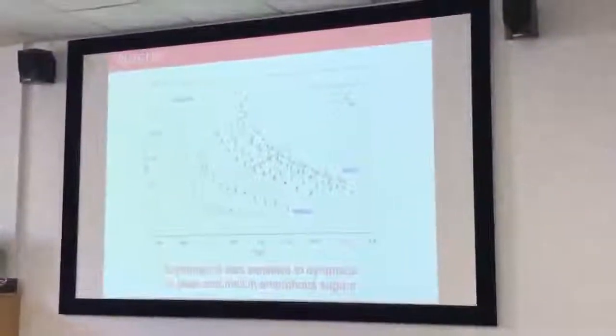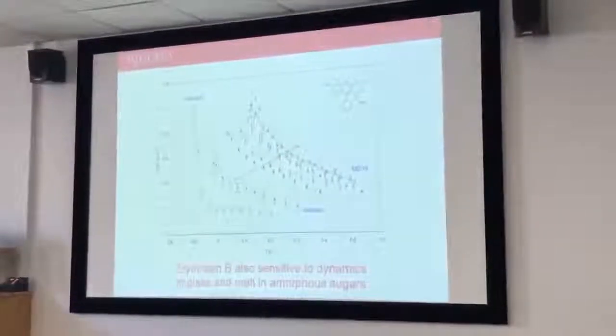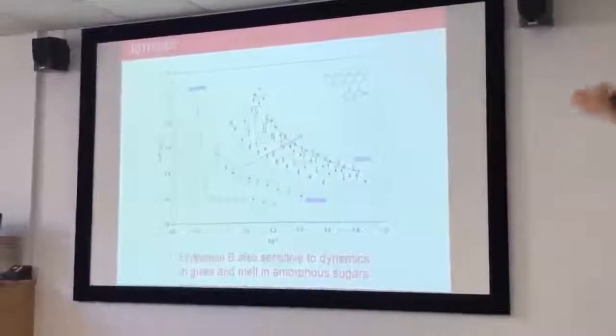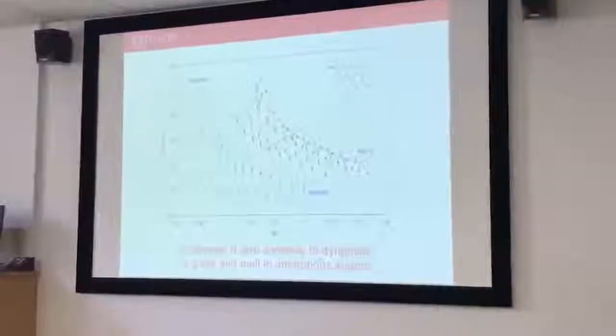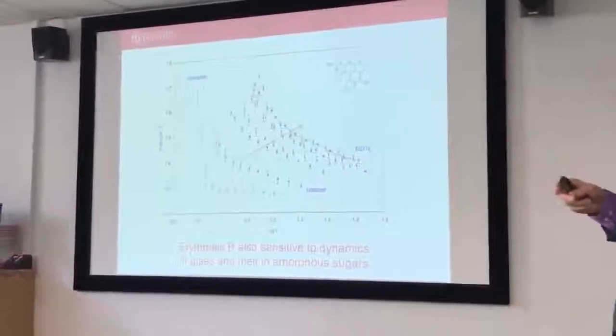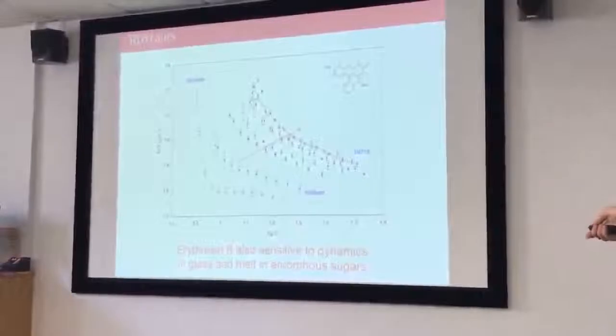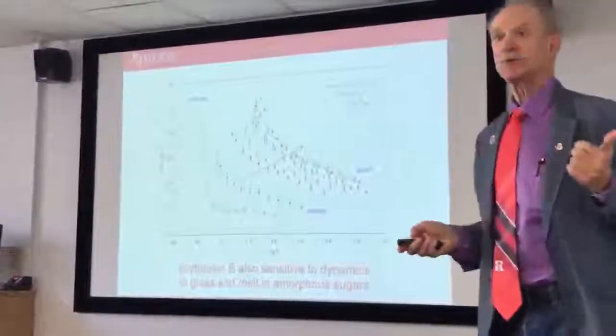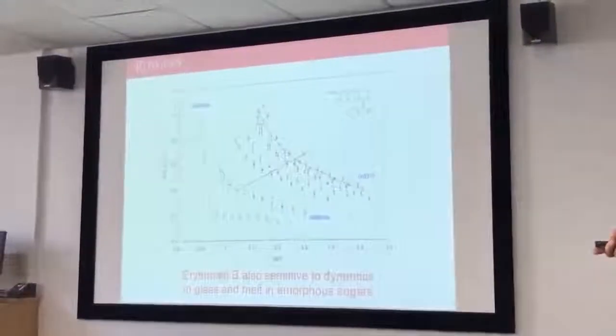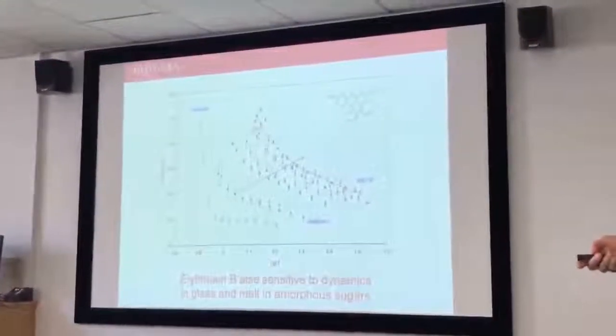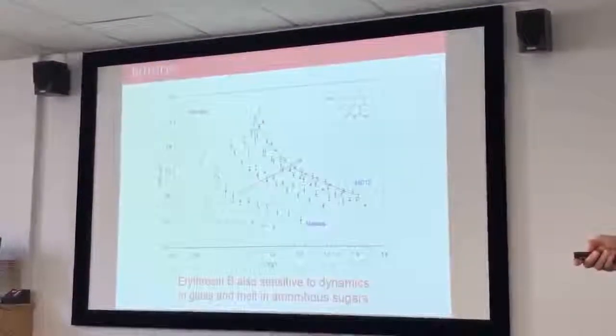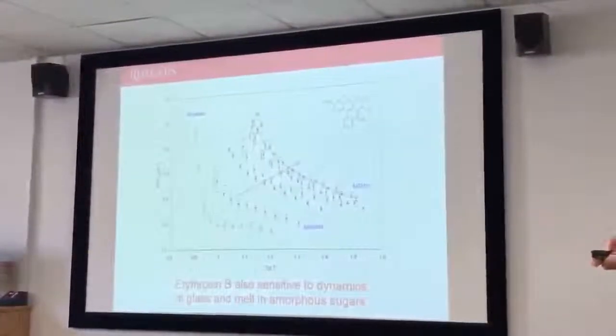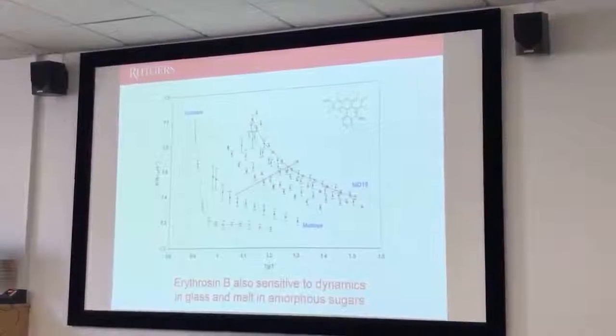The key thing is that we've also seen this with tryptophan. I don't show you the data. So at least four radically different, differently structured probes are all sensing this. And so we think that this is a universal property of a probe within a sugar matrix that we can measure. And the key thing is you can do these experiments in a microscope, so you can do it at a microscopic level. You can do it while the sugar is on a surface, so you can essentially make a measurement of what's happening locally within a complex group.